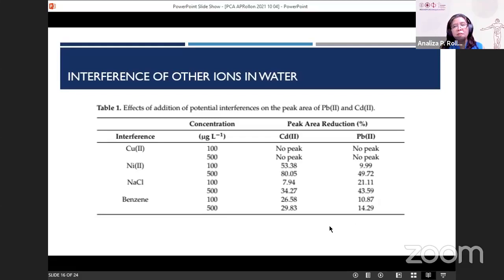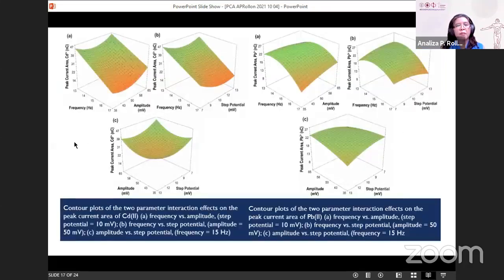But nevertheless, even if we can see this peak area reduction, we can actually correct this if we also know the relationship of the ion concentration with the peak area reduction. You can differentiate between the two metals, and you can also differentiate between different concentrations because of the linearity of the current versus the concentration of the metals.